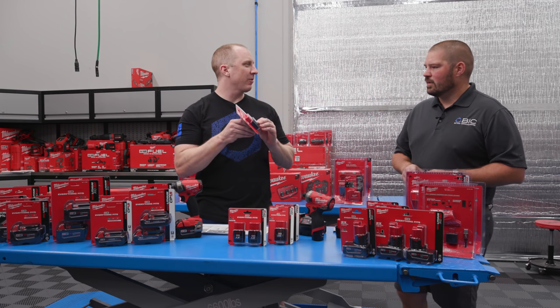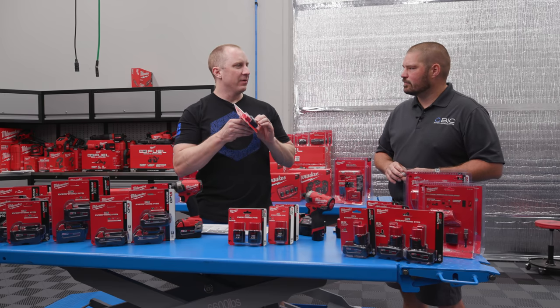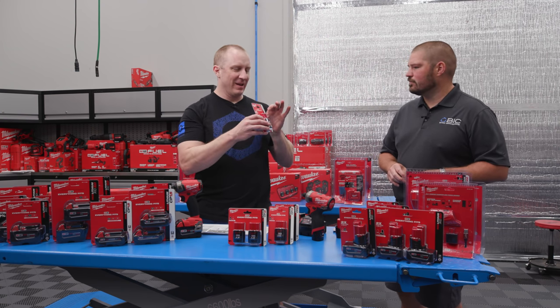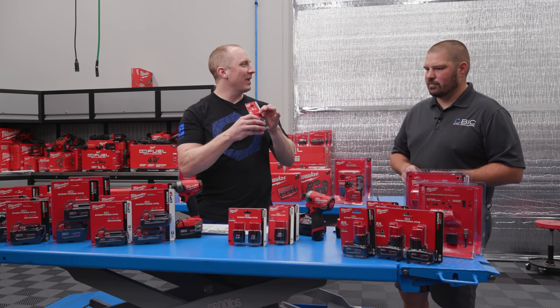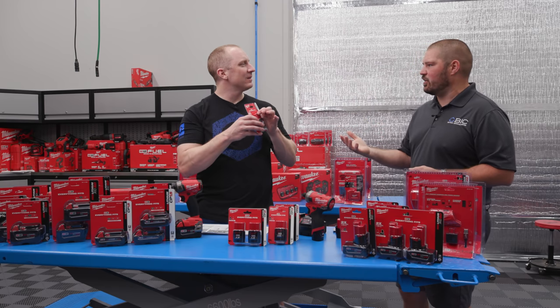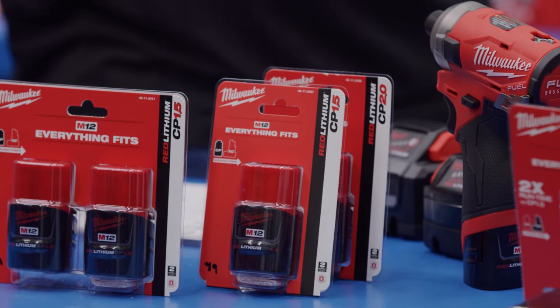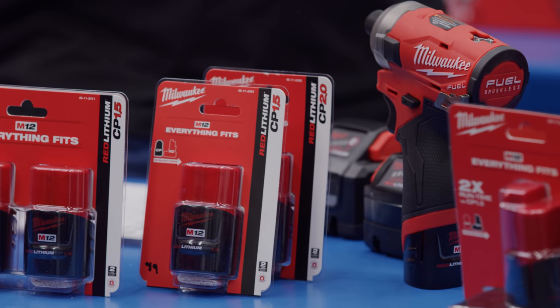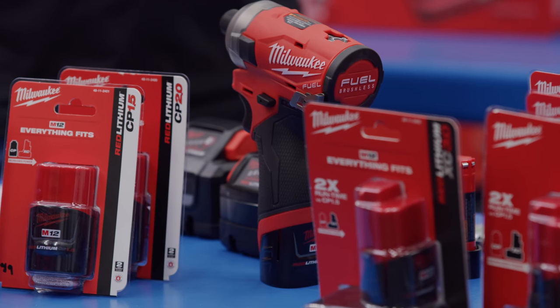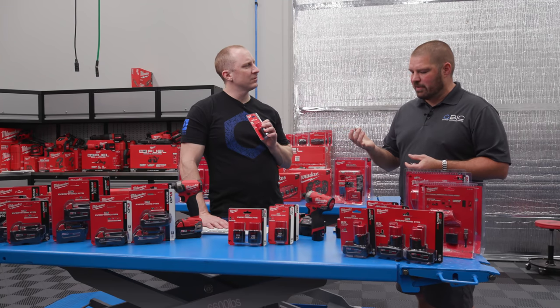When we say 3.0, we mean approximately three amp hours. They give it an approximate range of three amp hours. That would be 3,000 milliamp hours. They de-rate the batteries — just like Tesla, you don't ever get the full capacity, because they want the batteries to last through many cycles. Depending on whether you fast charge or slow charge, that can have an impact. The de-rating is intentional to ensure overall life on a lithium-ion cell.